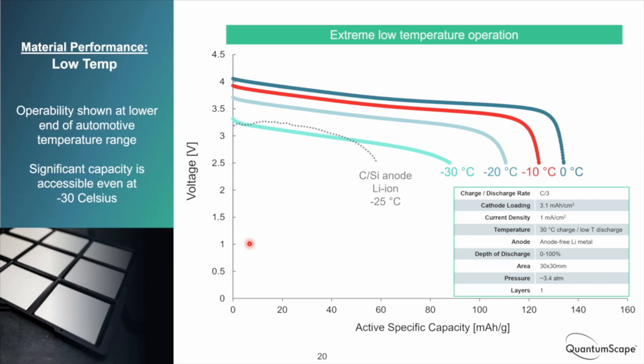So we wanted to show that our materials are capable of running across the full automotive temperature range down to minus 30 degrees C. This just shows a single C/3 discharge at decreasing temperatures from 0 degrees down to minus 30 degrees C. In between each of these discharges, we would do a C/3 charge at 30 degrees just to get the full charge capacity. So this is really just showing discharge capability of the material system.